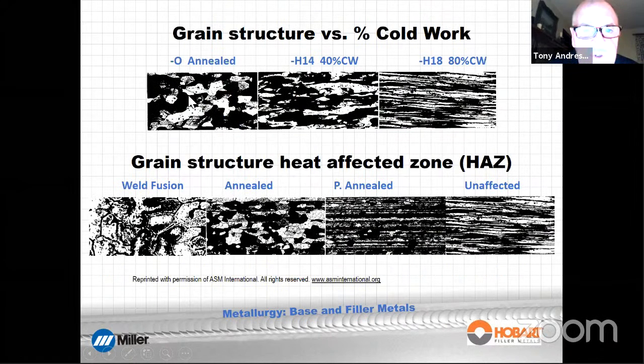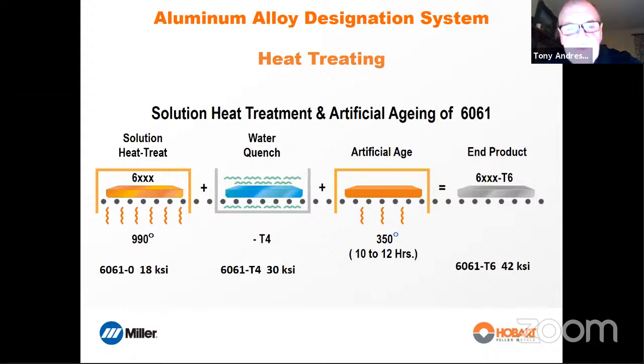This is what the grain structure of the O temper, the annealed, looks like. This is as we start doing more and more strain hardening, cold working, it's addressed as here, same difference. Strain hardening, cold working. This is taking it to an H14, which is elongating the grain slightly, and this is taking it to an H18, which is the maximum strength, which is elongating the material dramatically. But when we weld it, we take this material here and we take it back to the annealed strength here, like that, the O temper. Okay, so that's the non-heat treatable alloys we've just looked at.